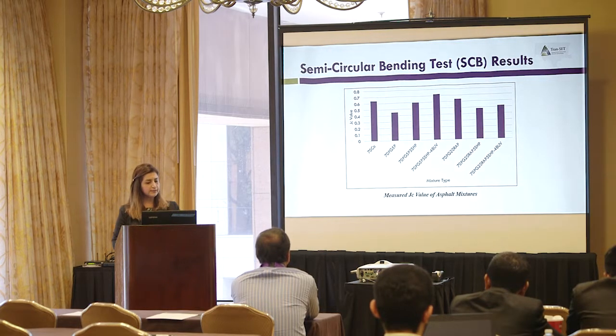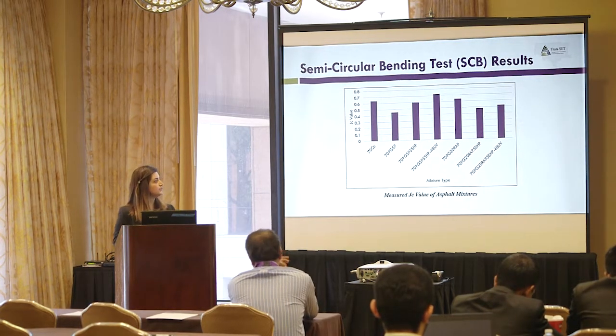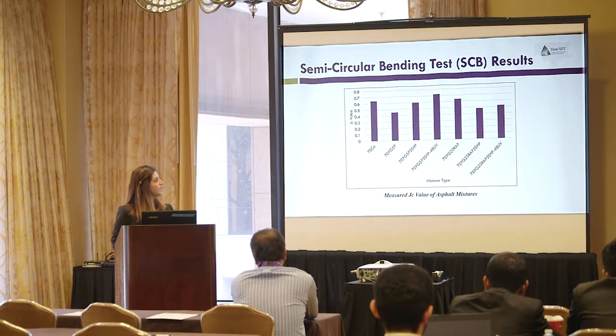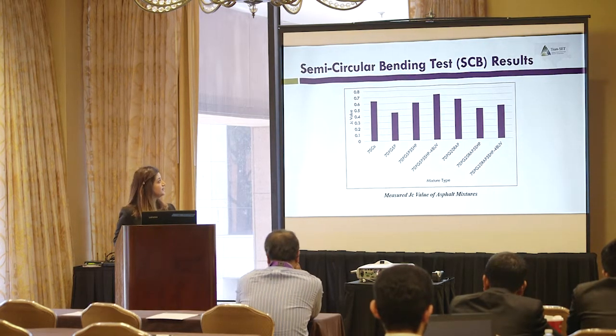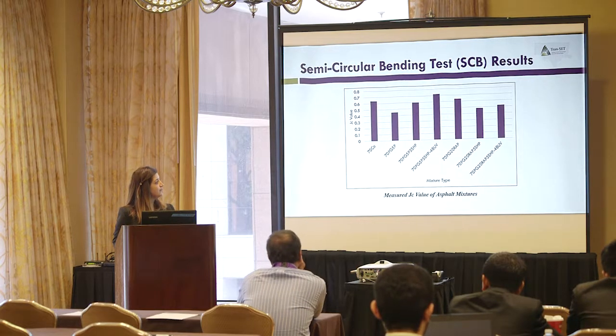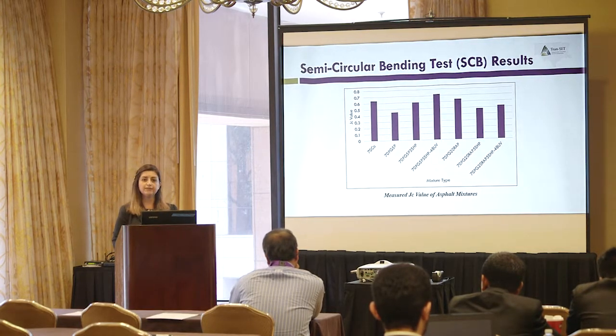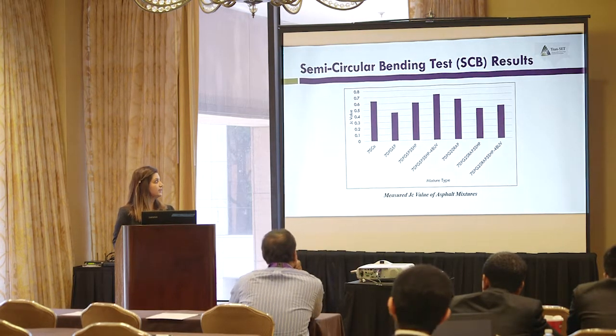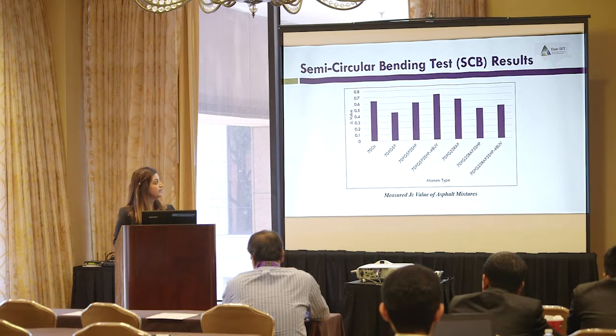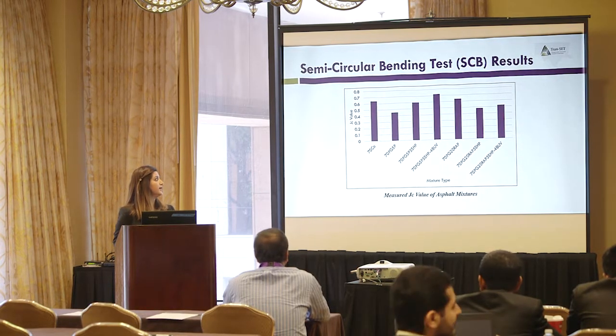The next result is from the semicircular bending test, which shows resistance to fatigue cracking of the samples. And we show the result based on JC value. When we added 5% RAS to our mixture, the JC value decreased significantly. When we added 5% of self-healing polymer to the mixture containing RAS, the JC value increased. And we can see that when we expose the samples to 48 hours of UV light, we have the highest JC value, which is more than 0.7.